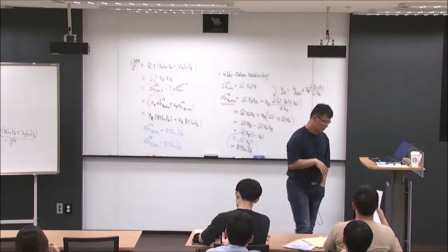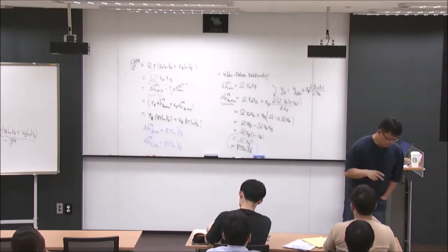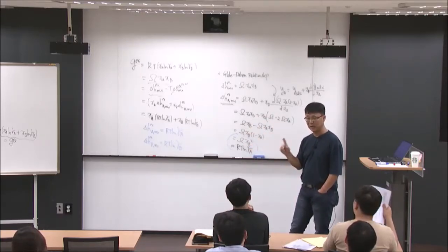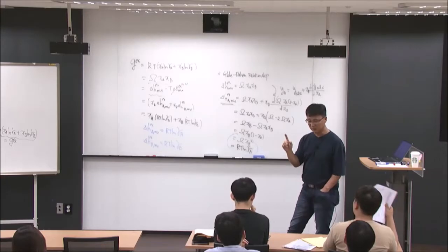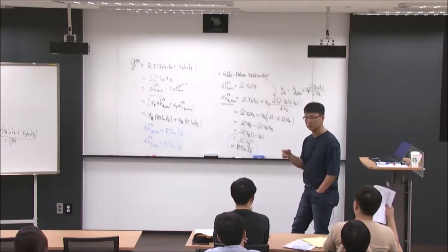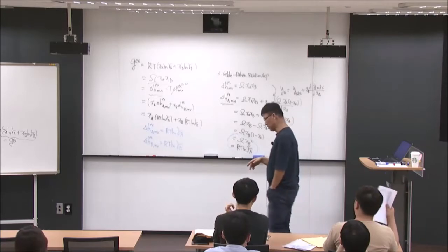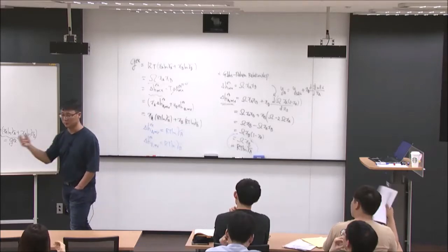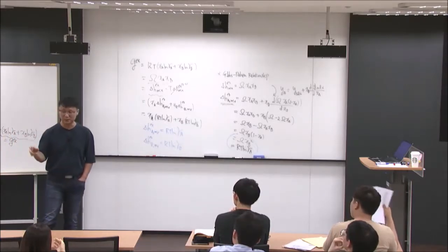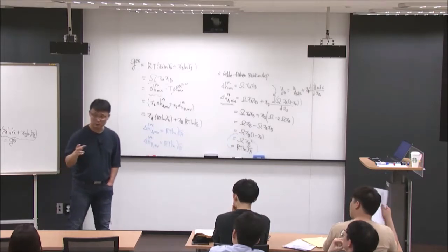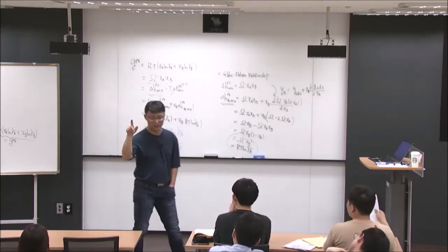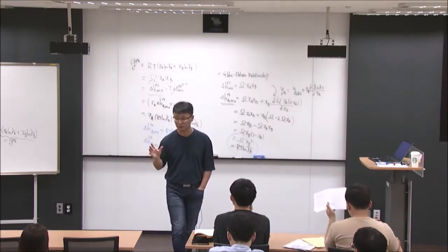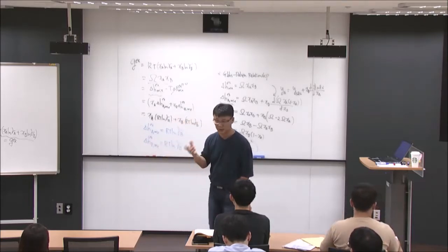Okay? And then there are very special cases. One case is the dilute solution and the other is the very enriched solution. When your component I in the solution is a dilute component, we can apply the so-called Henry's law. According to Henry's law, the activity coefficient of the species is constant. It's not changing with the composition. It is constant at the given temperature. However, the Henrian activity coefficient, so-called gamma I naught, can still be a function of temperature. It can change with temperature, but not with composition. That's Henry's law, the Henrian activity coefficient.